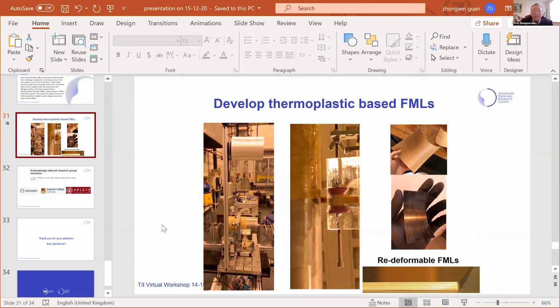When you do the reshaping, you're going to have some spring back, so in the mold design you need to predict how much spring back to accommodate. Here we are not talking about very small angle reshaping. We talk about maybe up to 90 degrees. You cannot say you want 180-degree reshaping; that will certainly cause damage. But these panels can be used to make, for example, door panels or tail wings, and that will be fine. For the fuselage it is fine because it's quite a smooth curvature. I see. Thank you very much.